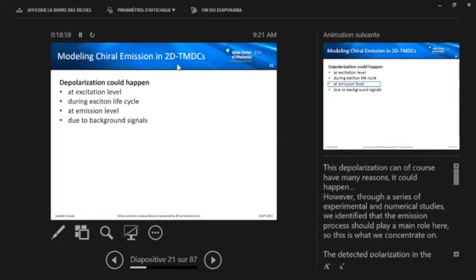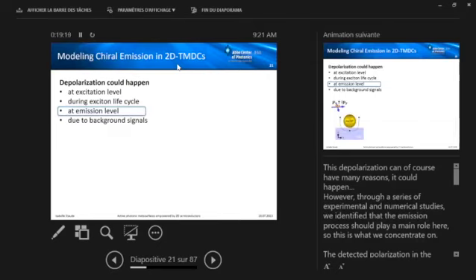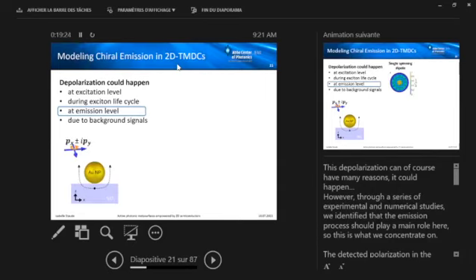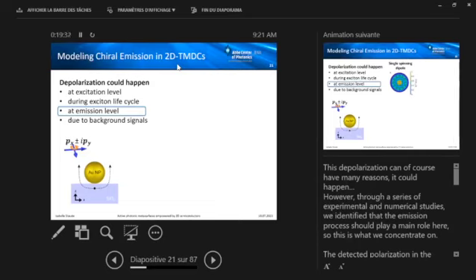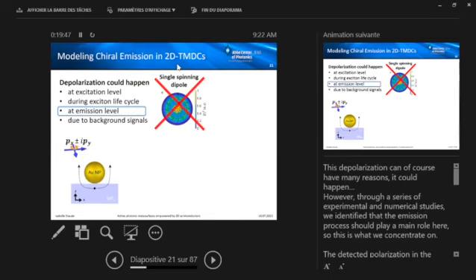So, where does this come from and how can we model this. So, depolarization could, of course, happen at many points, at the excitation level already, during the exciton life cycle, through some coupling and so on, at the emission level itself, or also due to some unpolarized background signals. However, we did a whole range of experiments and numerics, basically seeing that the effect at the emission level should be dominating this. And so then you look basically at the different modeling possibilities here, and the prevalent model in the literature is basically to use a single rotating electric dipole. So we situated this directly under the nanoparticle, and if we calculate for this, for the single rotating dipole, we cannot reproduce this depolarization, the polarization would just stay.